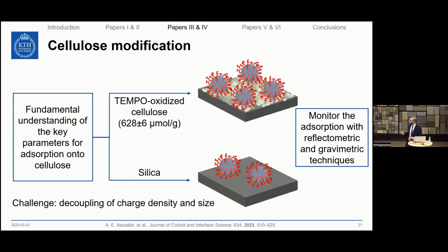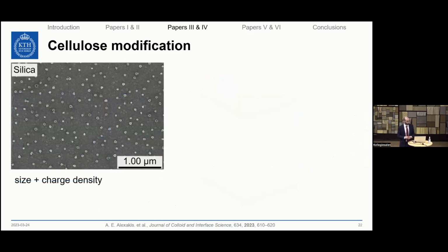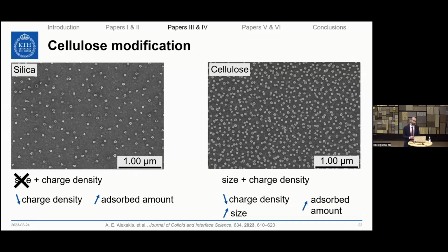So by adsorbing these nanolatexes onto silica or onto regenerated TEMPO-oxidized cellulose model surfaces, we monitored their adsorption with reflectometric and gravimetric techniques. In the case of silica, we found out that the main parameter that affects their adsorption was that of charge density. By reducing the charge density, the adsorbed amount was found to increase. However, for the case of cellulose, things are a bit more complicated. We found out that both the effect of size and charge density are equally important parameters, because in order to optimize the adsorbed amount, we had to reduce the charge density and increase the size at the same time.